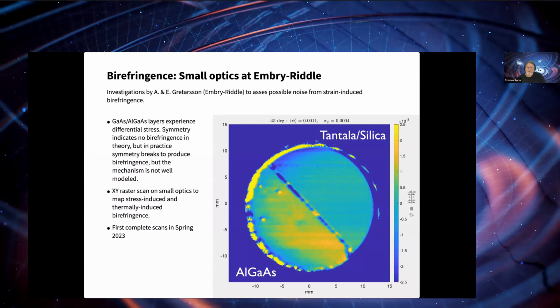Now, one thing that's different in AlGaAs versus amorphous coatings is that it's birefringent. And so there are investigations on both small and large optics. The small one's already underway. Andre and Ellie Gretarsson from Embry-Riddle have been conducting measurements on small optics where they raster over the surface. What's shown here is a picture comparing an amorphous coating, so this is a tantala silica coating, as was used in initial LIGO, and an AlGaAs coating, and you can then see the increased birefringence. So this is a relatively recent measurement, but their plan is to move to larger diameters and get more detailed scans as they develop the experiment.